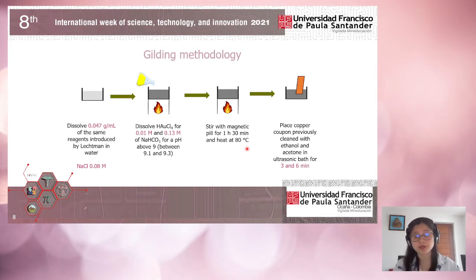After the solution was ready, we immersed the copper coupon, previously cleaned with ethanol and acetone in an ultrasonic bath for 3 to 6 minutes. What we did was to immerse the copper coupon halfway. After 3 minutes, we lifted it partially, and after 6 minutes, we totally removed it. This allowed us to have the same conditions for the 3 and 6 minute tests. It is important to notice that we use less gold precursor than Lechtman originally did and establish a concentration of sodium bicarbonate to achieve the pH above 9.